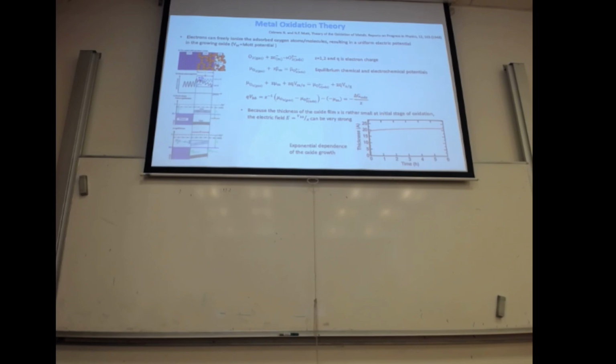So at the beginning you have this sort of reaction. The molecular oxygen gets some charge, a negative charge from the metal, and then it creates these adsorbates with some negative charge. Usually this Z is 1 and 2, and what we denote with Q will be an electron charge. So then what happens? You have an equilibrium of the chemical potential, the electrochemical potential. Basically you have the chemical potential of the oxygen molecule, the electrochemical potential of these electrons that you have, and then of the new adsorbate that you form.